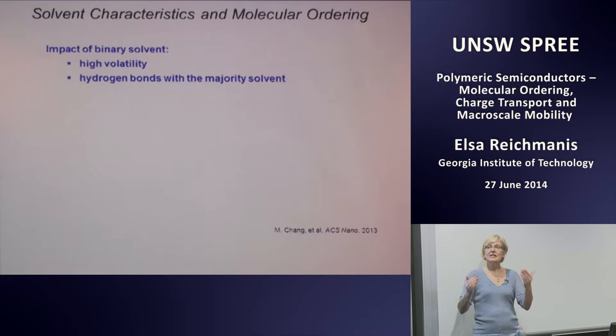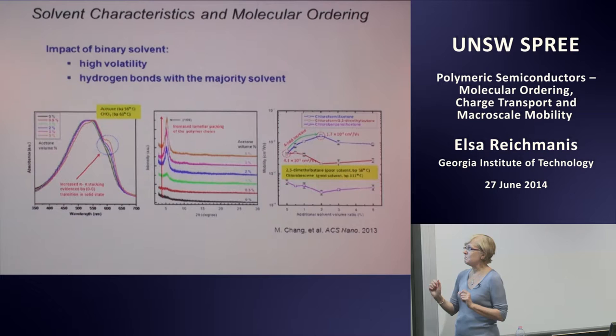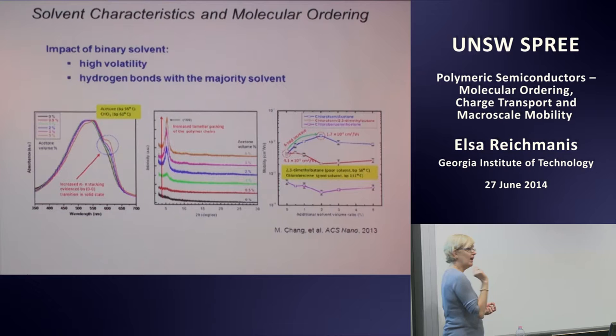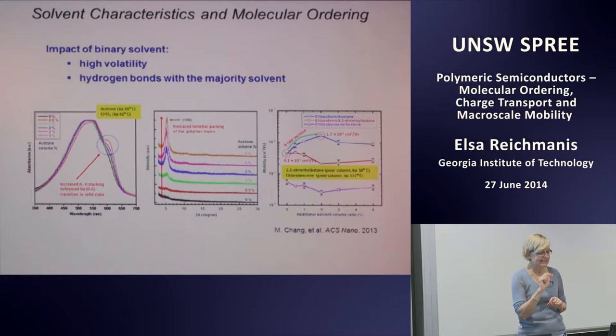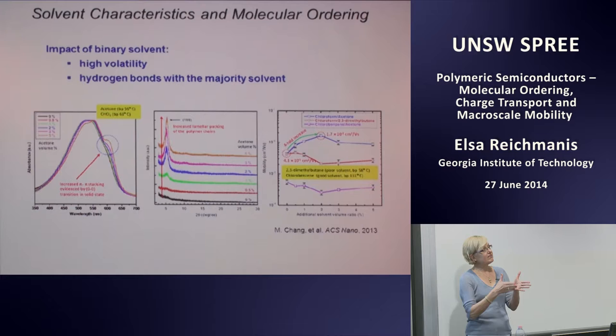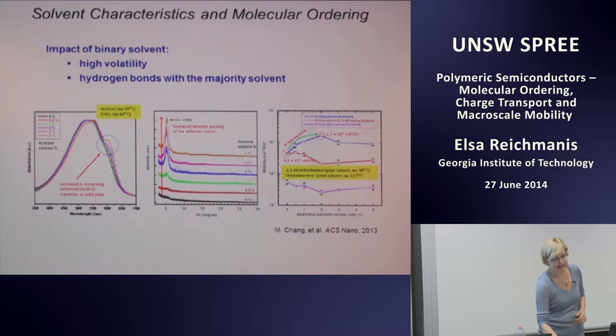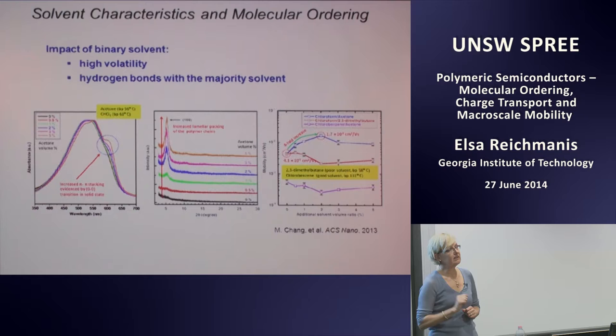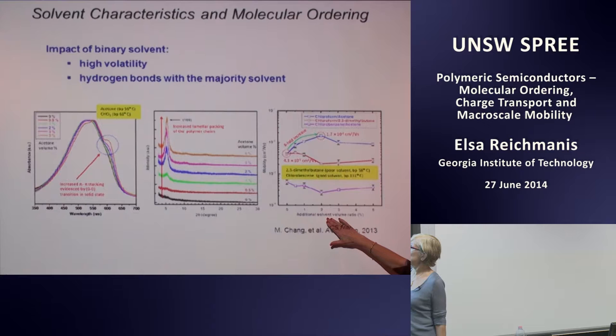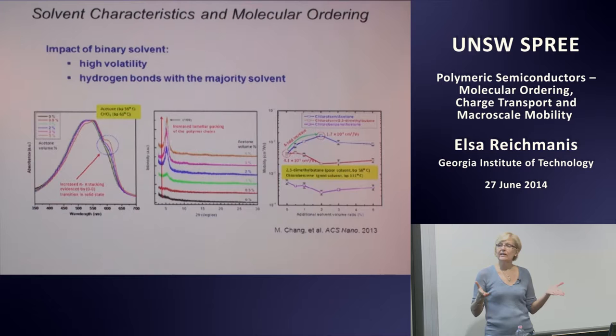All right, so by having a mixture, in this case of acetone and chloroform, by adding only about 2 milliliters or 2 weight percent acetone to a largely chloroform solution, we don't really change the solubility characteristics of P3HT in the solvent at all. But what we do change is how the thin film processed from that binary solvent behaves. In particular, there's an increase in crystallinity of the material as we add a little bit of acetone to this chloroform mixture. And at about 2 weight percent acetone, we also see a fairly dramatic increase in the mobility of that system.